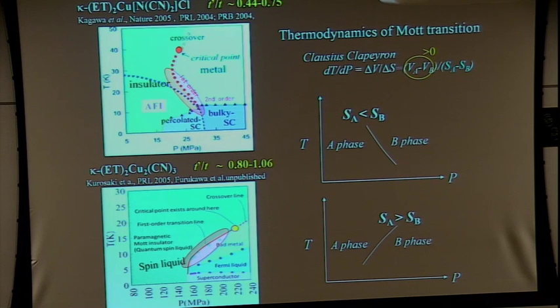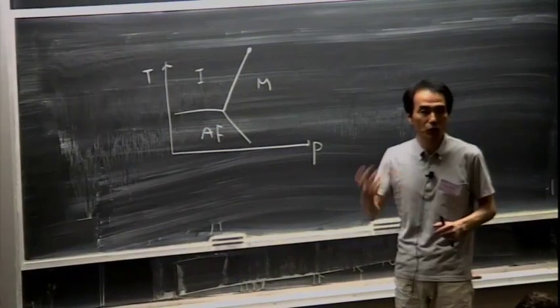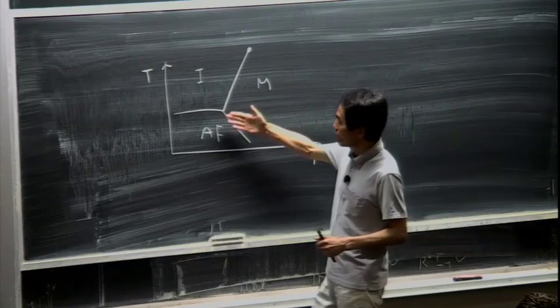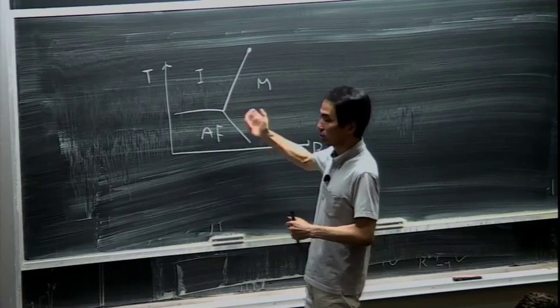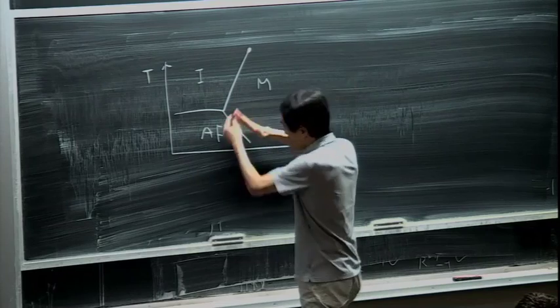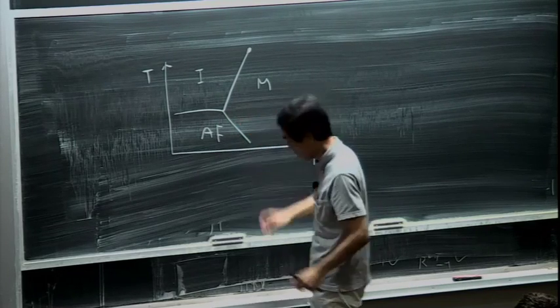Pressure and temperature. First order transition between temperatures and metal. And this is the insulator, paramagnetic insulators, and this is AF. This is for three-dimensional materials. There is no prominent short-range fluctuations. So once antiferromagnetic order occurs, the entropy balance is suddenly reversed. This is the three-dimensional case.